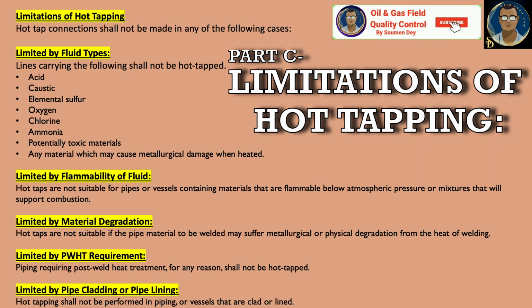that will support combustion. Hot tap is limited by material degradation. Hot taps are not suitable if the pipe material to be welded may suffer metallurgical or physical degradation from the heat of the welding. It is limited by PWHT requirement. Piping requiring post-weld heat treatment for any reason shall not be hot tapped.